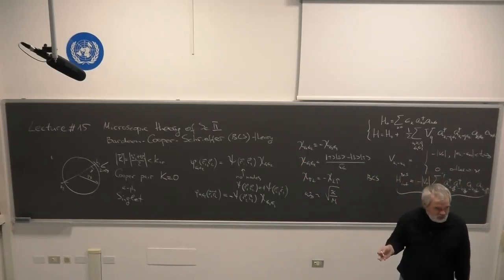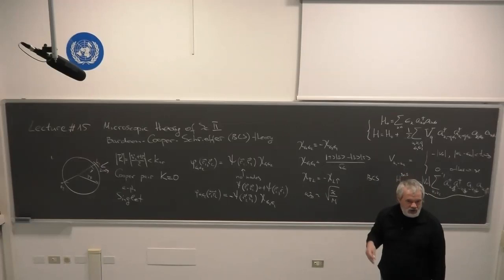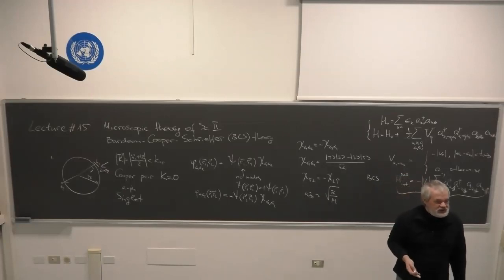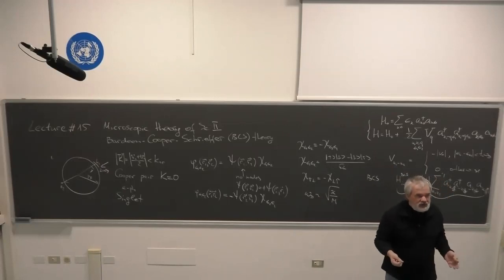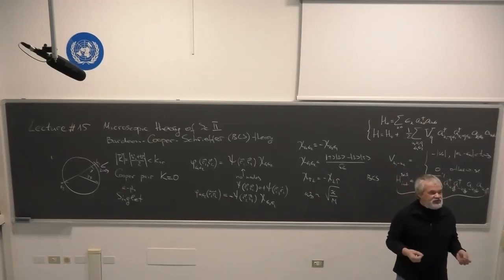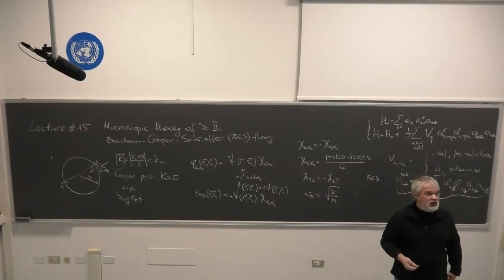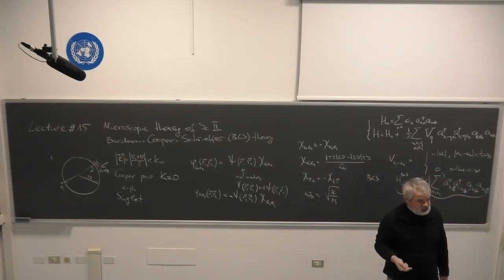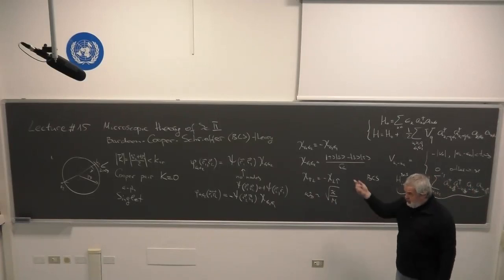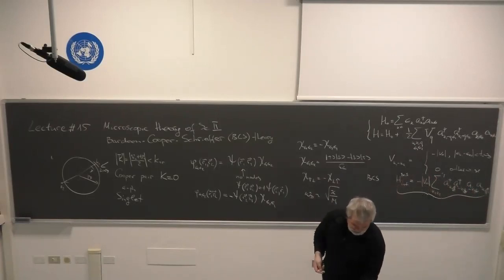I introduce the strength of electron-phonon interaction, and at the end of the calculation we will see that the equation will contain microscopic parameters of your material, namely the strength of electron-phonon interaction and the density of states at the Fermi level. So it is material specific, and knowing these parameters, one can describe the behavior of the spectrum, the instability of your ground state, and actually much more than that. You will see how to apply this theory in the tutorial on Monday, but we are about to derive the equation. Good.